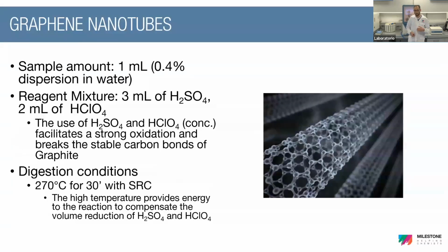So if we see the methods that we use for the digestion of that sample, we use an acid mixture of sulfuric acid and perchloric acid. As I said, perchloric acid is very rarely used, but this is a good example of a sample that really needs the use of these chemicals, because without them it's not really possible to have the complete digestion of it. Normally, for most cases, we use nitric acid and peroxide, but in that case, we really need a strong oxidation energy, let's say, to break the chemical bonds.